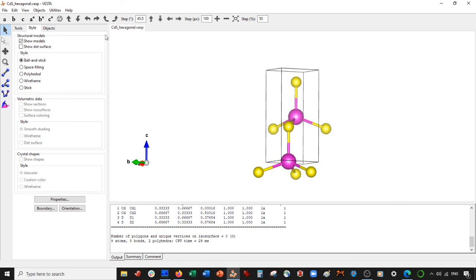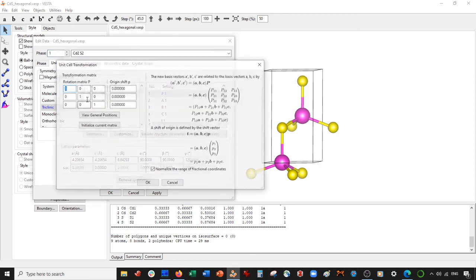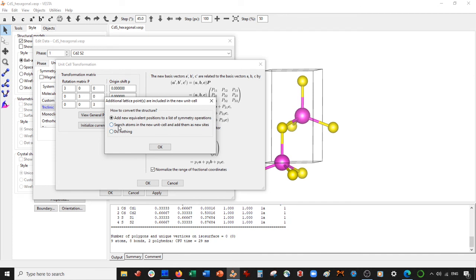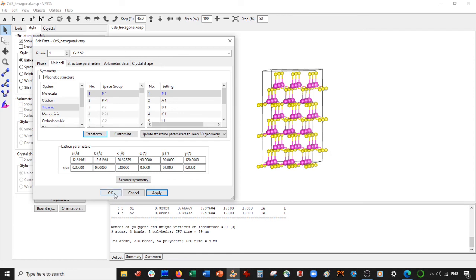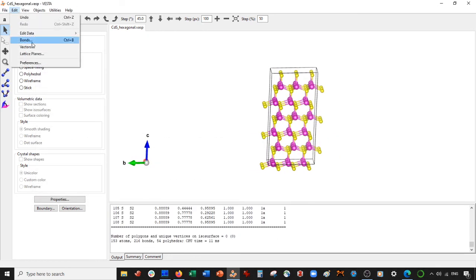So I have the cadmium sulfide unit cell here — the hexagonal unit cell. I'll go to Edit > Edit Data > Unit Cell and expand the cell three by three by three. Now it's very important here that you press the middle button 'search atoms in the new unit cell and add them as new sites' so it updates the positions. Press OK, apply, OK — now you have 153 atoms.